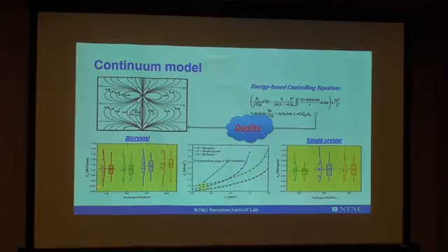And we can observe that the MD simulations predict values of K1D from about 1 to about 1.25. And this is fairly located in the region predicted by the continuum model. So it suggests that the proposed model can fairly predict the dislocation behavior.